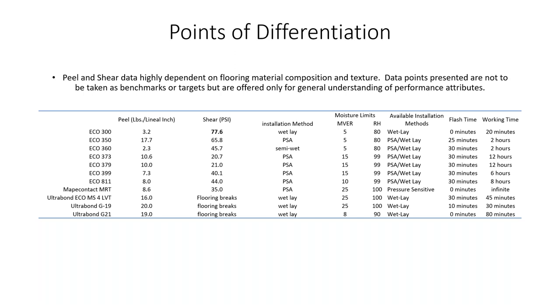373, our great product we use for LVT, has great peel, which is indicative of a very sticky product. 20 pounds of shear strength is more than adequate to keep LVT in place as long as you've got the temperature control in order. Obviously, it is less in terms of shear strength than one of our wet set materials, but it's still a great product for what it does. 379, a new one that we've got, again, great aggressive grab, is a 10 pound number, 21 to 25 pounds on the shear strength. So again, good for shear and so on.